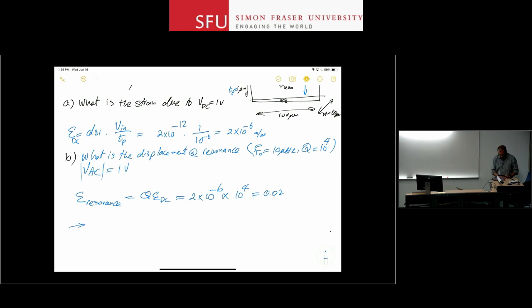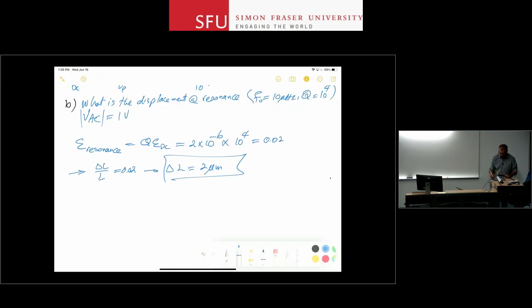So meaning that delta L over L is 2%, or 0.02. And for a length of 100 microns, you can show that delta L therefore is 2 micrometers. So at resonance, this device is becoming 2 microns longer and shrinking by the same factor, right? So that's the amplitude of motion. It goes up to 102, comes back to 98. That's a lot of motion, right? But we get that range of motion because at resonance, the same force that you had before gives you Q times more effort, Q times more output.